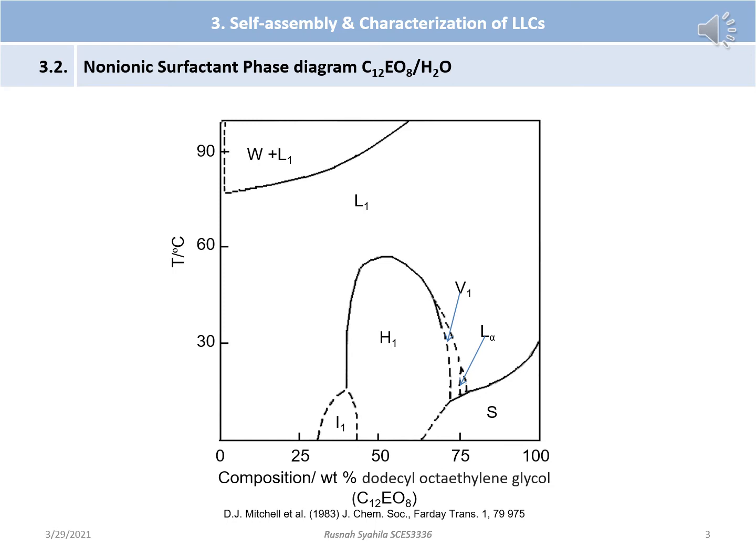This behavior is characteristic of non-ionic surfactants containing polyoxyethylene chains, which exhibit reverse solubility versus temperature behavior in water and therefore cloud out at some point as the temperature is raised. Glycols demonstrating this behavior are known as cloud point glycols and are used as shale inhibitors.